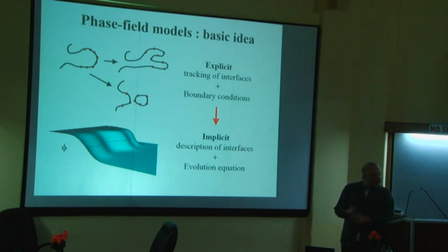Well, the traditional way is to put some marker points. That is, you have some points on the interface. Then you can approximate the interface, say, by a polygon. And then you can put this, say, in a finite element mesh, and solve the diffusion equation on this finite element mesh. You can calculate the velocity for each segment. Then you can move the segments forward.